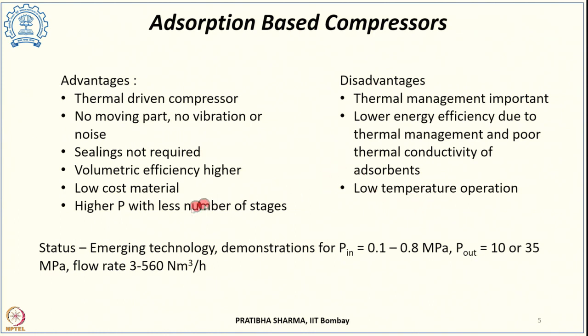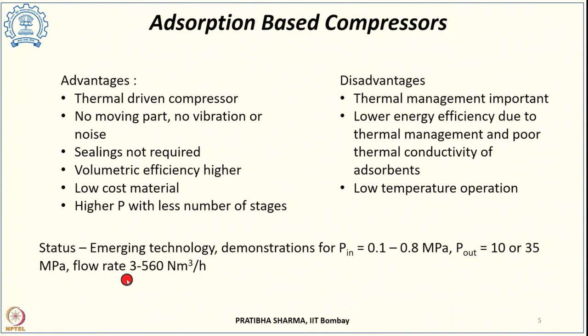Low temperature operation adds to cost and reduces efficiency. This is an emerging technology. Demonstrations in literature show input pressures of 0.1 to 0.8 MPa yielding output pressures of 10 to 35 MPa with flow rates of 3 to 560 normal meter cube per hour.